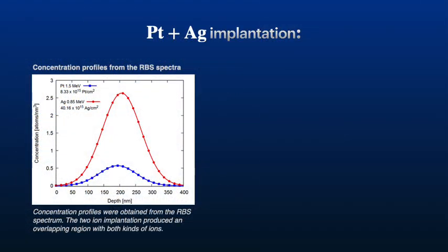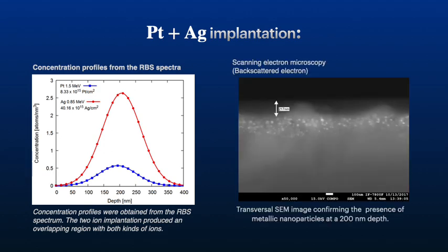A first series of pristine substrates were initially implanted with 1.5 megaelectronvolt platinum ions. After that, the sample was annealed for 120 minutes at 1000 degrees Celsius to promote the formation of platinum seeds and their growth. 0.85 MeV silver ions were implanted afterwards, and a second annealing was carried out for 60 minutes. The Rutherford backscattering analysis confirmed that both ion distributions overlapped at a projected range of 200 nanometers. Scanning electron microscopy confirmed the formation of nanospheres with radii distributed around 3 nanometers.